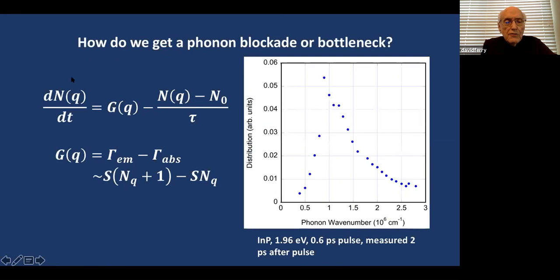This is the equation I showed you before. Now, this expands to the emission of phonons by the electrons minus the absorption of phonons by the electrons. Now, the emission is proportional to N_Q plus 1, absorption to N_Q. Okay. Now, here's how you create a blockade. N_Q is usually small. Here it's really big, 0.05. But on the scale of 1, that's still a small number. But if I could get N_Q up above 1, so these two terms start to cancel each other, then I create a blockade when the electrons can no longer emit phonons.